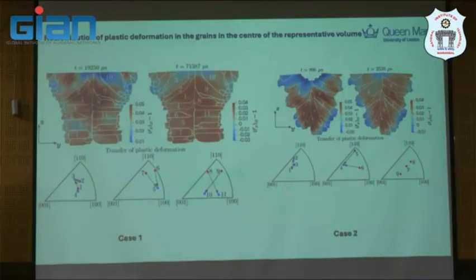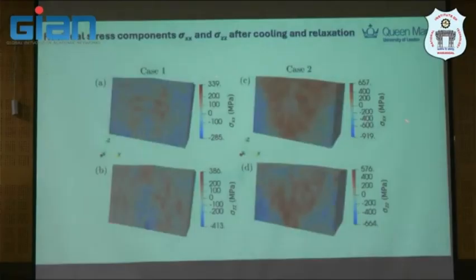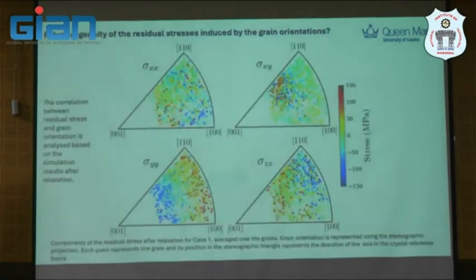If you do a high fidelity model, it can reveal this, and then they try to extract from the simulation what happened in the residual stress profile after cooling and relaxation. Residual stress components are in XX and ZZ. The question he asked is quite interesting: how is the heterogeneity of this residual stress induced by the grain orientation or not?